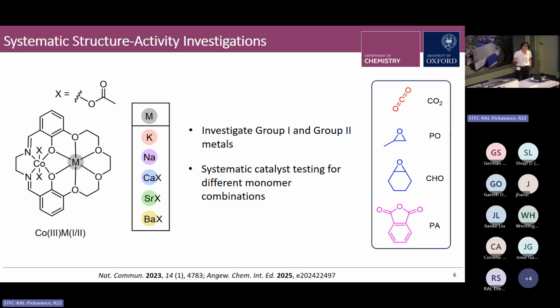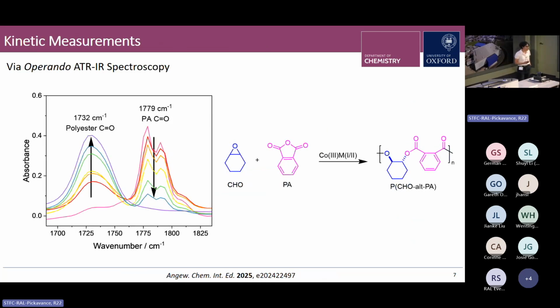But before I show you the results of the catalyst testing, I wanted to briefly outline how we measure our kinetic parameters and how we monitor these reactions. So we monitor the reactions using operando IR spectroscopy, which enables us to track absorbance as a function of time for various different carbonyl stretching frequencies. So in the case of this epoxide anhydride copolymerization, we can monitor the increase in polyester concentration by the increase in absorbance of the peak at 1730 wavenumbers. We can also monitor the decrease in anhydride or monomer concentration by the decrease in absorbance of the peak at 1780 wavenumbers.